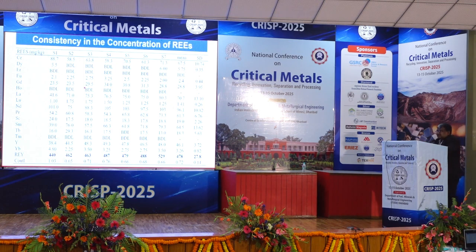For any industry to invest, there should be consistency in the data. It's not that someday we got a good concentration, so we did a continuous evaluation for 7 days, and each day multiple samples were collected. See, the standard deviation is quite good, and you can see the data of the total rare earth is also consistent, so one can go for investment in fly ash confidently.